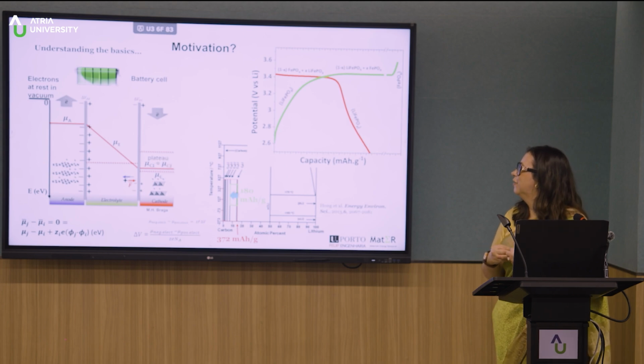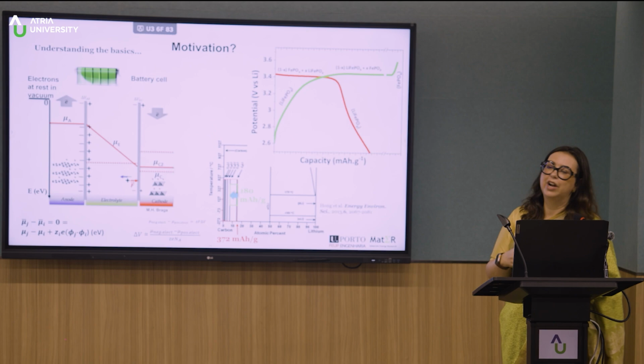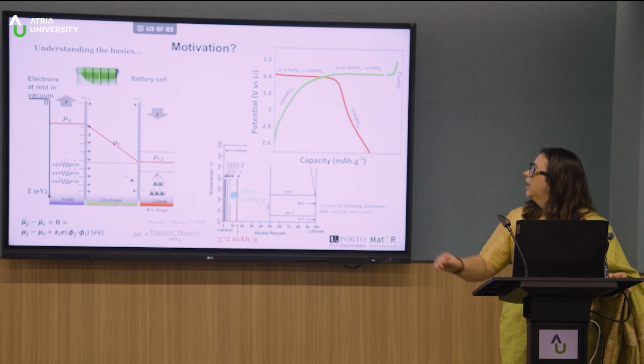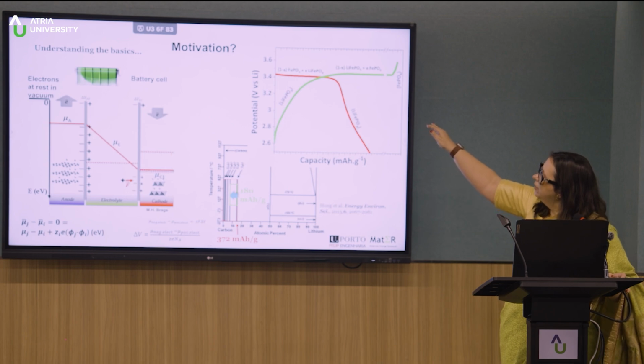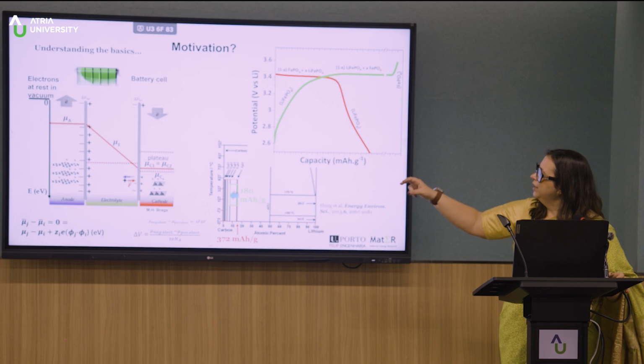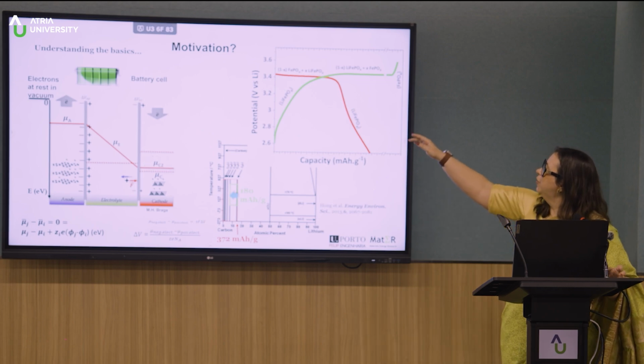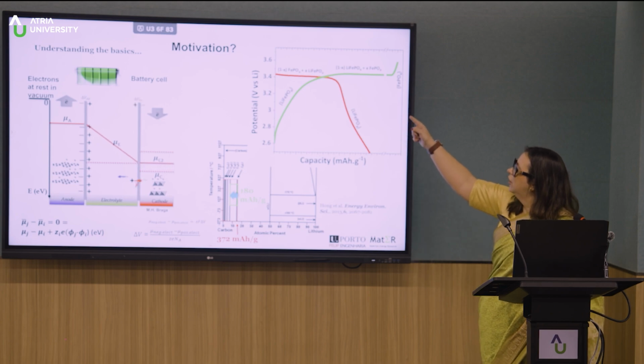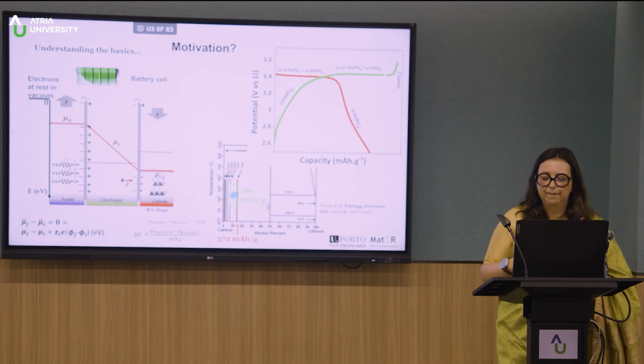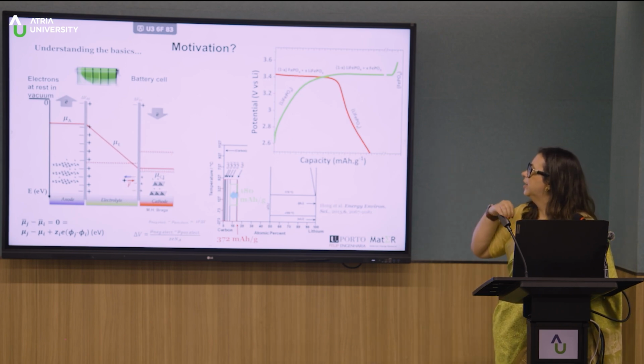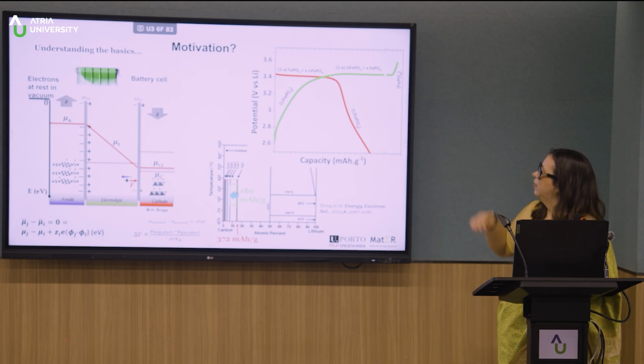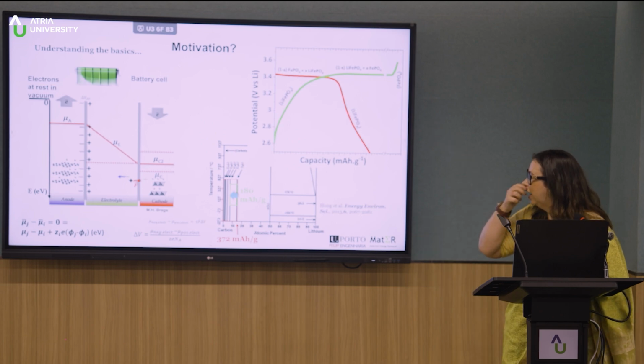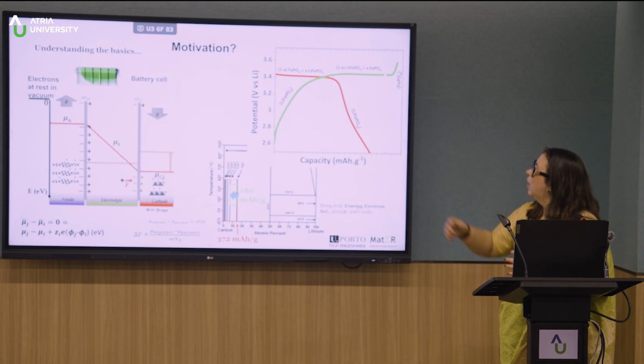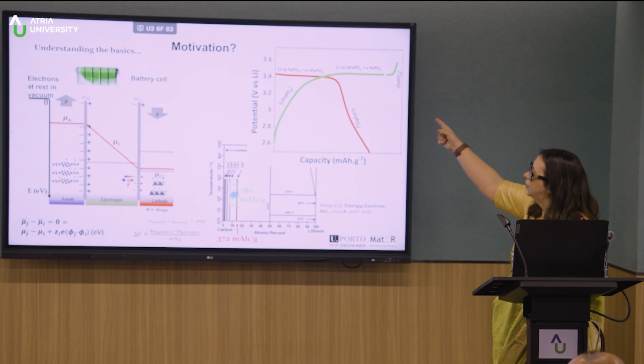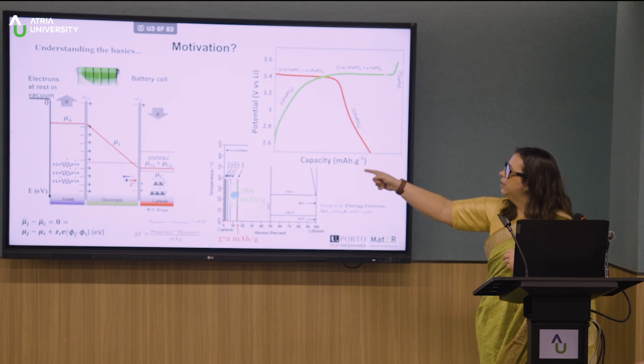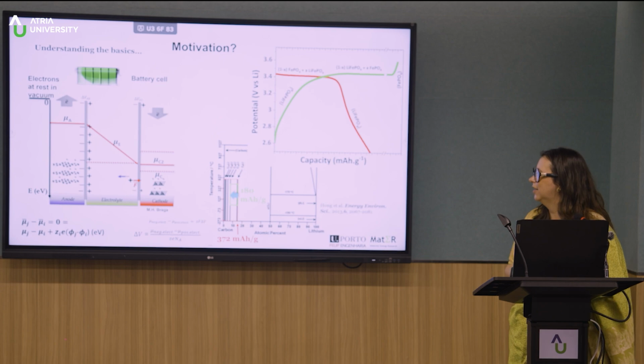Then there are several types of batteries. There are like LFP, where you have an equilibrium plateau, and while you are at the equilibrium, the two phases will have the same chemical potential, and so you can keep the voltage while on the plateau, while one phase is increasing and the other phase is decreasing. So we can keep the voltage. So what we want is to have this plateau to be larger and larger. So we want to have this equilibrium to last for the highest capacity we can get.